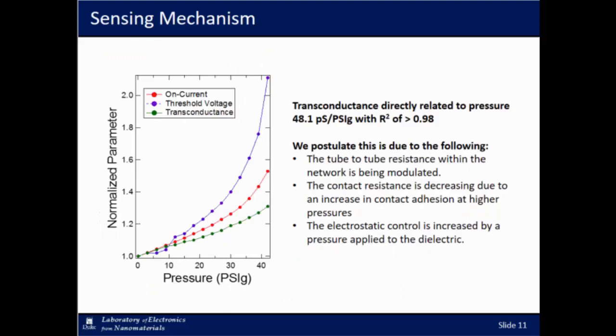So the mechanisms of how this sensing is working, we have a few different things that we'd like to postulate, to hypothesize. We think maybe the tube-to-tube resistance within that network is being modulated. Another thing that could contribute is the top contact resistance being modulated with increasing pressure. And lastly, the dielectric is fairly new and hasn't been printed that often, so we're not sure of the properties of it. They might be changing under pressure, giving us better electrostatic control at higher pressures.